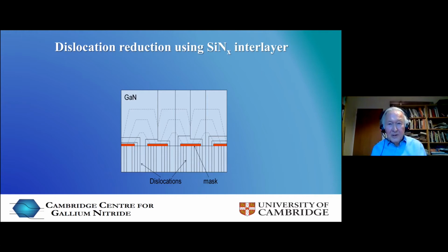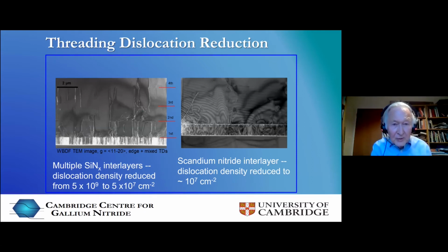And you might think this is an incredibly rare event, but actually it's quite a common event. And we get 2 orders of magnitude reduction of dislocation density. And you can see this visually on this slide. So if you look at the left-hand slide, the bottom portion shows this very high density of vertical dislocations coming up. And then where it says first, that's the first interlayer we put in of sub-monolayer silicon nitride, and the dislocation density is drastically reduced. Then if we wish, we can put in a second layer and a third layer and a fourth layer. And in this sample, the dislocation density is reduced by 2 orders of magnitude.